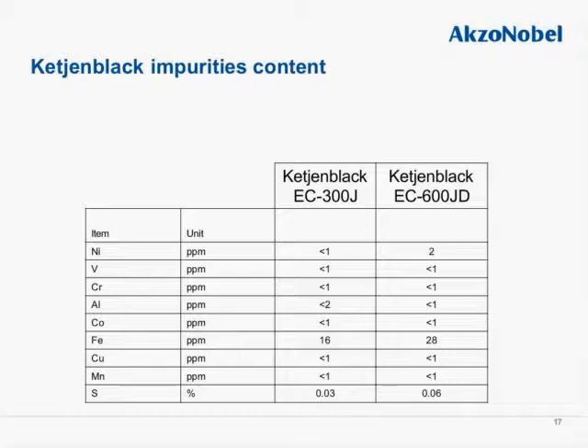So other impurities, the reason why the ash content is such low levels is because the heavy metal and other metal content impurities are present at a very low level in each of these products. As you can tell, we test for nickel, vanadium, chromium, aluminum, cobalt, iron, copper, manganese, sulfur, just to name a few. We actually have a longer list. These numbers are not reported in the certificate of analysis of the Ketjenblack product line, but we conduct a periodic analysis and issue reports on the impurity content.